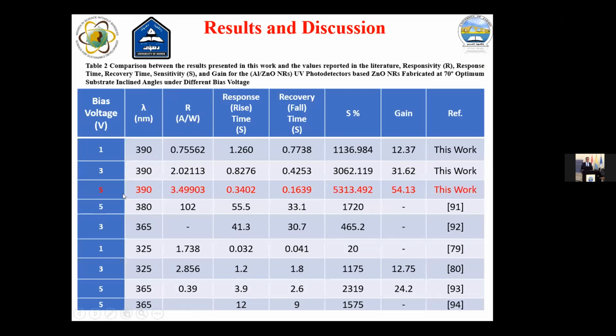We can see for 5 bias voltage we have the high responsivity, and we compare with the recent literature work in this field. Just one is higher than my result, and the other is not. But we can see the response time is very rapid, and the recovery also, and the sensitivity is higher, about 5,000. And again, for this UV photodetector it is about 54 percent.